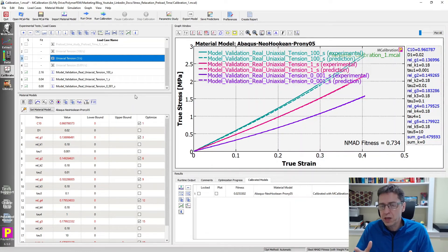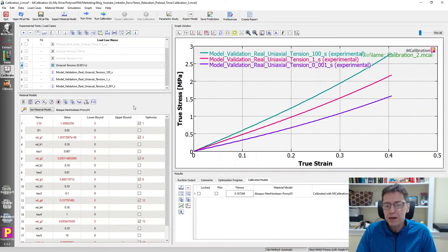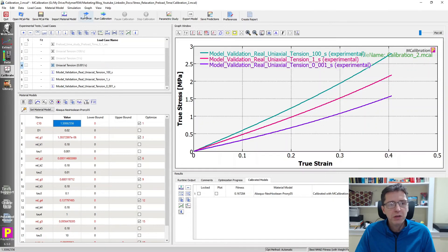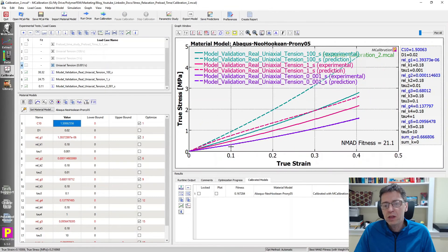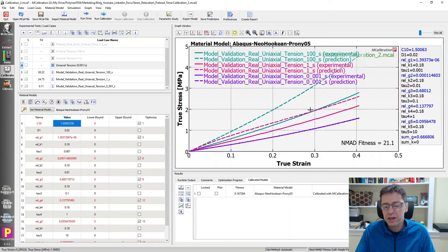Now let's see what happens if we didn't really know the preload time - say we assumed it was one second, which is 10 times too long. Here are the results for the second material model calibrated with an error in the preload time. We see, as mentioned earlier, a 50% error in the C10 parameter. How does that translate to stress-strain predictions? The prediction of the really slow strain rate is still good - at really long times, we have a good prediction - but at high strain rates, we get a very large error. The NMAD fitness is 21. The green and red predictions are way off the experimental data, illustrating the importance of having the correct preload time.